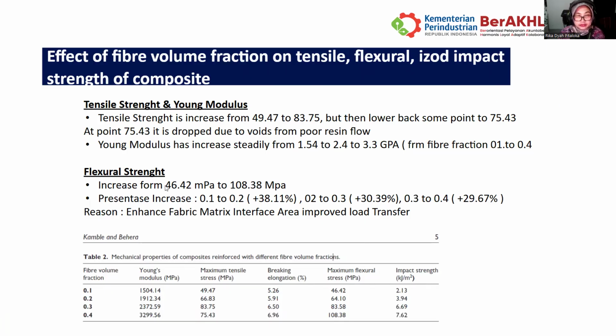But for the flexural strength, we can see here that as the fiber volume fraction increases, the strength increases from 46.42 to 108.38.